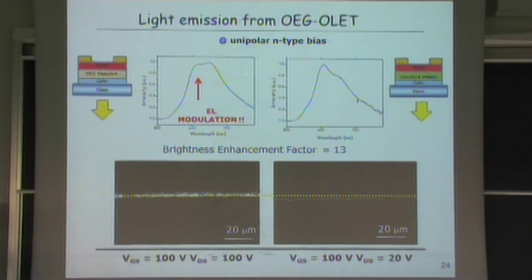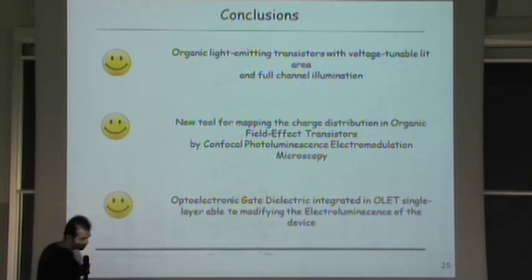Let's see light emission from these devices. But it's important to note the electromodulation in the spectra of our modified device, and also the light emission here. You can see again there is no emission under the electrode, so it's a good point, and also the brightness enhancement factor is one order of magnitude, so good.